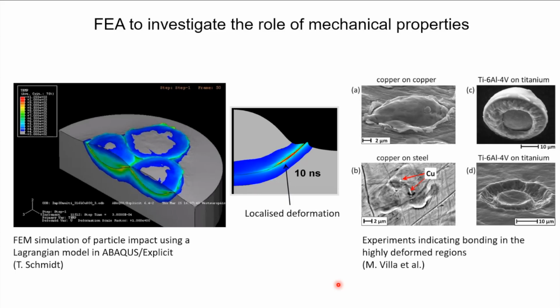What was a breakthrough then was looking at the single particle impact experiments, what they call wide tests. You could see that at the rim of the craters, there were some signs of bonding because there were residues of the impacting particles on the substrate. And later on, that was shown for other materials, here for titanium, that apparently the bonding does occur from the rim and then it propagates towards the south pole of the particle. So apparently there was some message here that, based on this mechanical analysis, this localized deformation has some role in bonding.